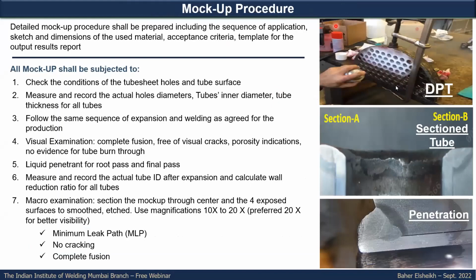For the mock-up procedure, here is some recommended procedure for the mock-up. First, you need to be careful before applying the mock-up that you should have a detailed procedure of what should be applied. Here we are providing some suggested or recommended step-by-step procedure for the application of the mock-up. First, you have to check the condition of the tube sheet hole and the tube surface. Measure and record the actual hole diameters, the tubes' inner diameter and tube thickness of all tubes, and for the holes as well, and this has to be well recorded and marked.